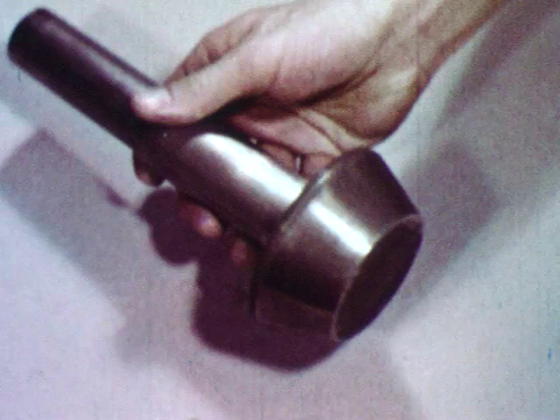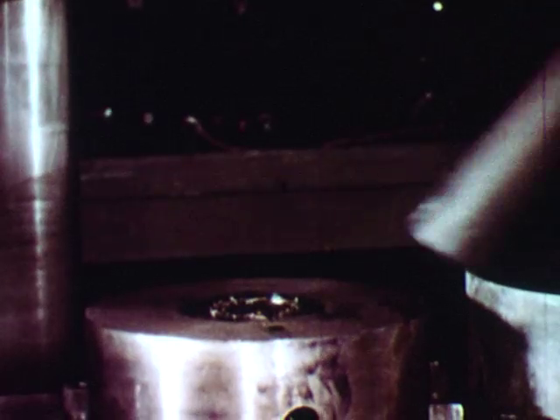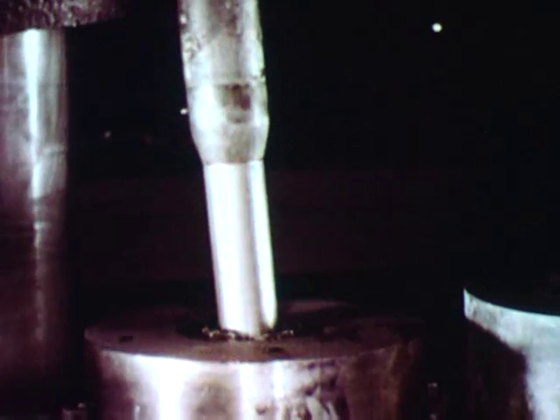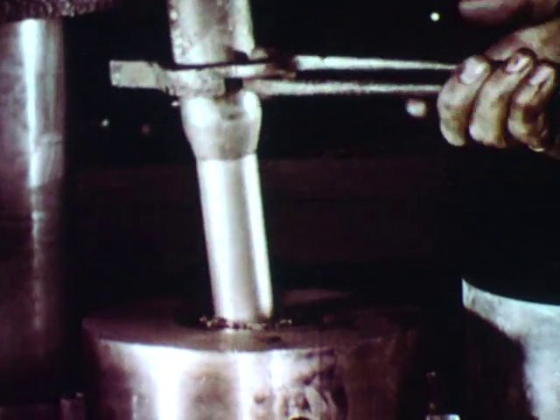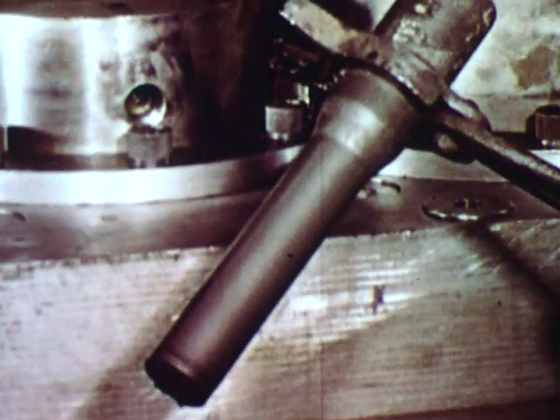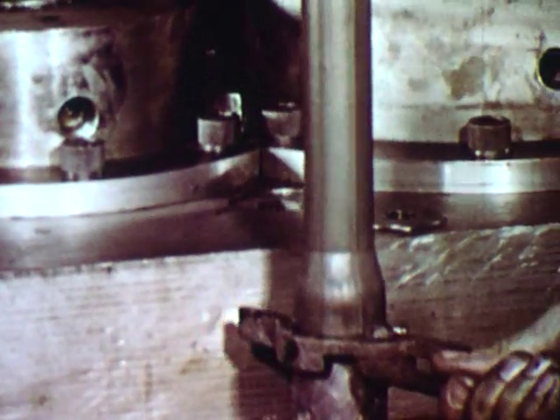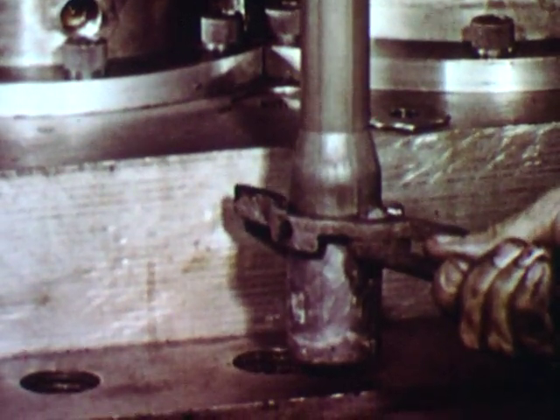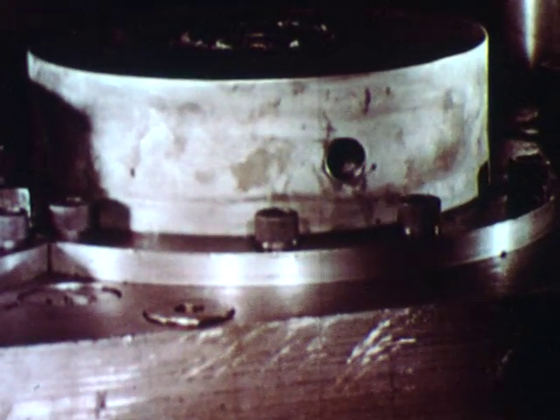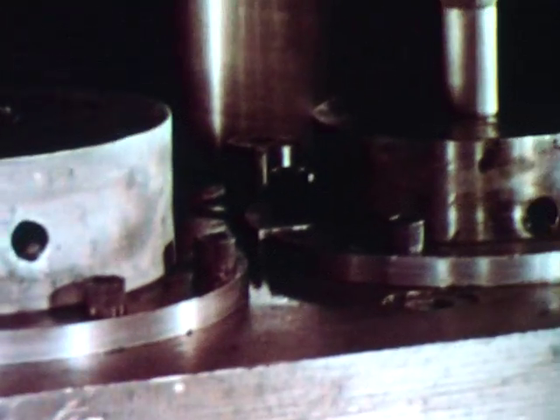Could this 6-pound stem pinion be cold forged on a machine of this type? Here we see this pinion cold forged experimentally on a 3,000-ton maxi press. The 8620 steel bar is 1 7/8 inches in diameter and 8½ inches long. A phosphate and soap coating serves as the lubricant.